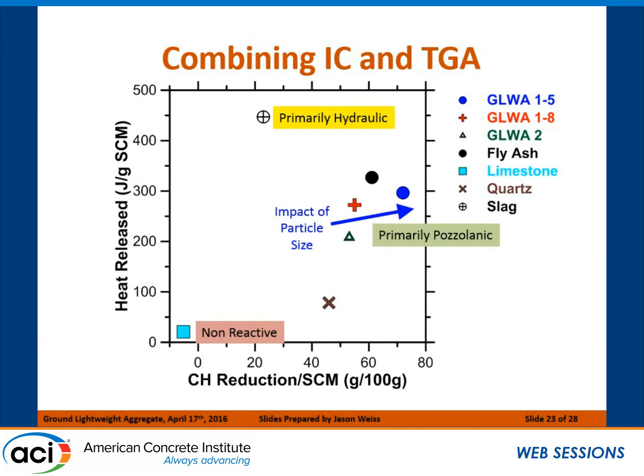Something that's staying here close to zero, it's a very non-reactive material. Non-reactive in terms of pozzolanic reaction or hydraulic reaction on its own. Doesn't mean it's not important in the overall system. Doesn't mean it's not going to change the performance. But the limestone on its own is not what's reacting. We can look over here and we can say slag. We know that that's got some of its own hydraulic capacity to it. Very high heat release versus a relatively low amount of calcium hydroxide change.